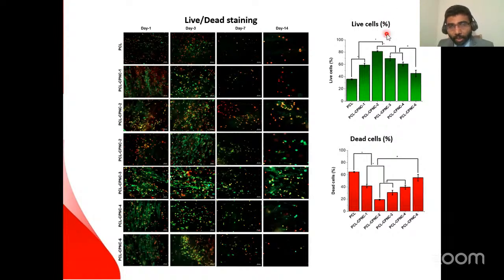That is this right side graph. The green one shows the living cells, and the red one, the bottom one, shows the dead cells. We can see that compared to the bare PCL membrane, more cells were living when PCL was incorporated with the oxygen generating material. However, at higher concentration, we observed a little decrease in the viability because of a slight toxic response, because the calcium peroxide can generate reactive oxygen species. So we need to use an optimal level of material.